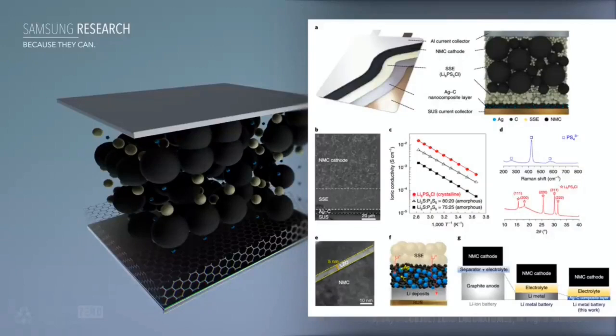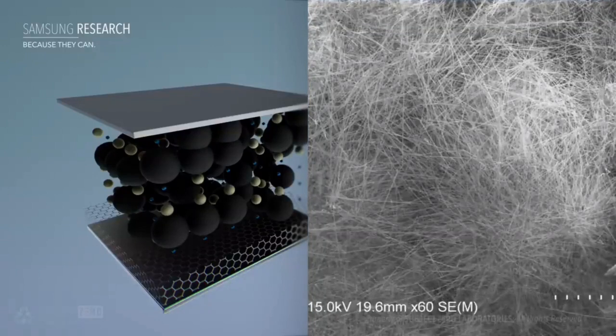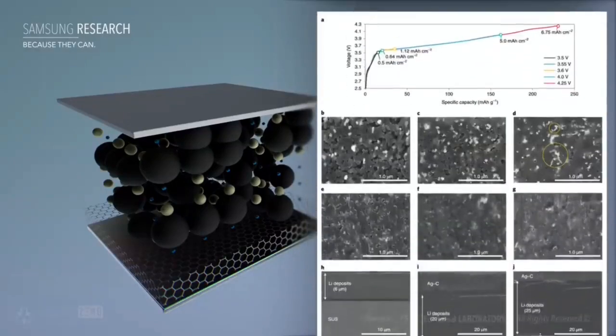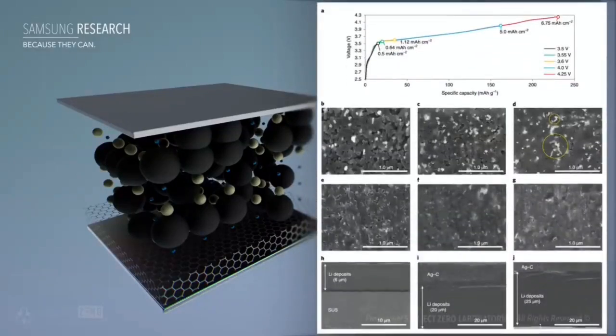Most solid-state battery technologies proposed to date have some sort of nanomatrix layer compound, like silica for instance, that is used to absorb lithium ions. By removing this layer and having only silver atoms playing the part of the matrix to guide the ions, you can effectively introduce more cathode into the mix, increasing the overall energy density of the battery to 900-plus watt-hours per liter. This approach also increases battery lifetime efficiency by 200%.